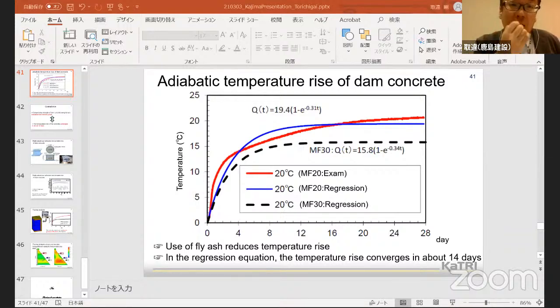This slide shows the adiabatic temperature rise of dam concrete we measured, and this is the relation between days and temperature. Use of fly ash reduces temperature rise. This red line is the experimental data, and the blue line is the regression data applying these equations. The black line shows the MF30 data. In the regression equation, the temperature rise converged at about 14 days.